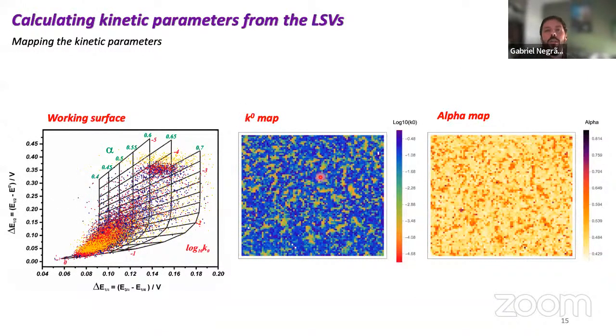And one could make an argument that this has some correlation with topography, but if you do just a line scan here, and we try the same region to get K0 values and topography, there's no correlation there. It just looks like noise. There's no correlation at all. We did that for a few lines. So there's no correlation with the topography.